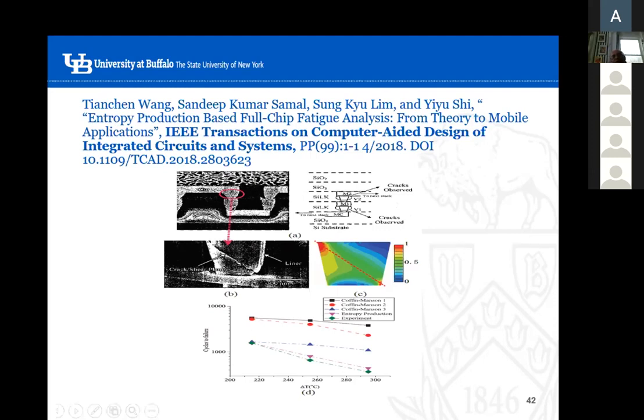However, there are many layers, but each layer has a different coefficient of thermal expansion. Each layer expands at a different level. As a result, these solder joints are subjected to cyclic shear when you turn it on and when you turn it off. And then continuously, they are subjected to cyclic shear because of this heating and cooling down when you turn it off. So this delta T is the temperature change in the ambient.